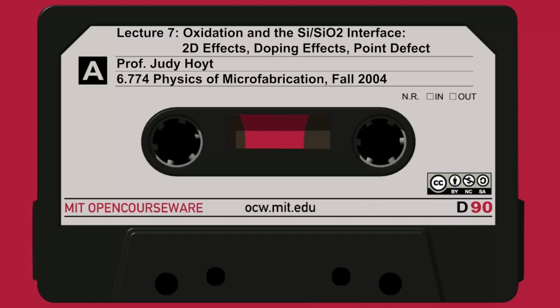It was very narrow. And lo and behold, underneath where you're doing the oxidation, the boron diffuses a lot. So it becomes very wide. So they come in here and they disturb the boron diffusion. They enhance it. And so the junction here, the width of this boron profile, is now quite wide underneath the oxide where it was growing. Under the nitride, where there was no oxidation taking place, I have inert diffusion. There's very little boron motion.